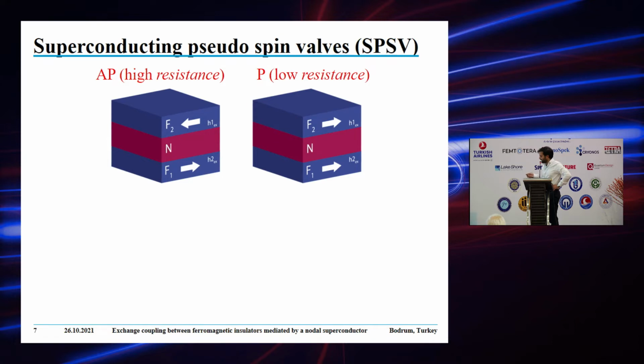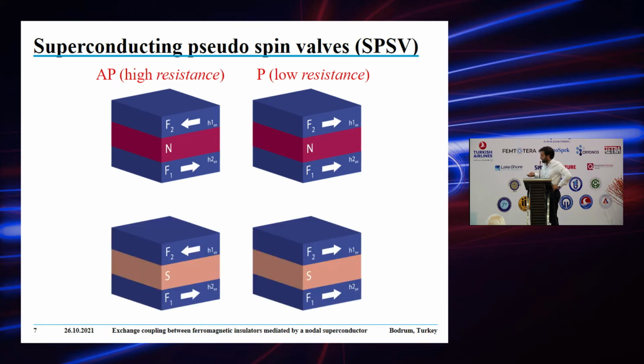Again, we want to reproduce this device that has two states, high resistance and low resistance, but in the superconducting state. So we have to replace the normal metal in between with a superconductor. The physics here is different, but qualitatively you get the same effect, because what matters now is the pair breaking effect that the exchange field of the ferromagnet has on the Cooper pairs inside the superconductor. Where both ferromagnets point in the same direction, the net pair breaking effect is higher, because these are two vectors that you are summing at the two interfaces.